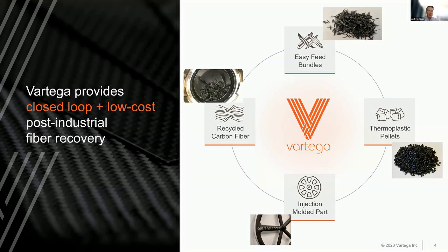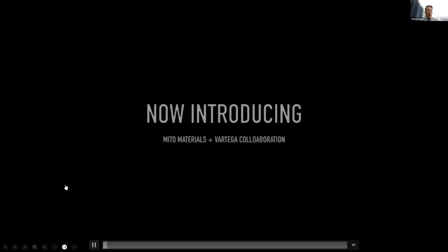So we've got compatibilized binders, polymers, urethane, polypropylene typically, that we'll use as a sizing or a binder to hold those bundles together. And as Haley alluded to, we're able to incorporate MITO's Ligra functionalized graphene into that sizing chemistry, into that binder. So it actually adheres directly to the fiber and helps to further compatibilize with the polymer resin that's going into the thermoplastic matrix. So we did that, and for CAMX, wanted to show a little video that the MITO team put together.